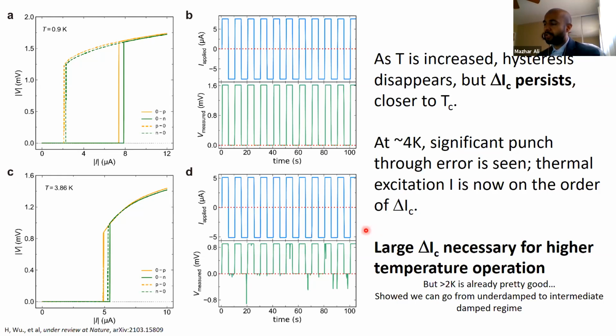This is at 4 Kelvin where it starts to break. I think as long as you're above 2 Kelvin, that's already pretty good. And we can go from the under-damped regime to the intermediate damped regime, and the whole thing still works, which is important for some applications I'll talk about later.